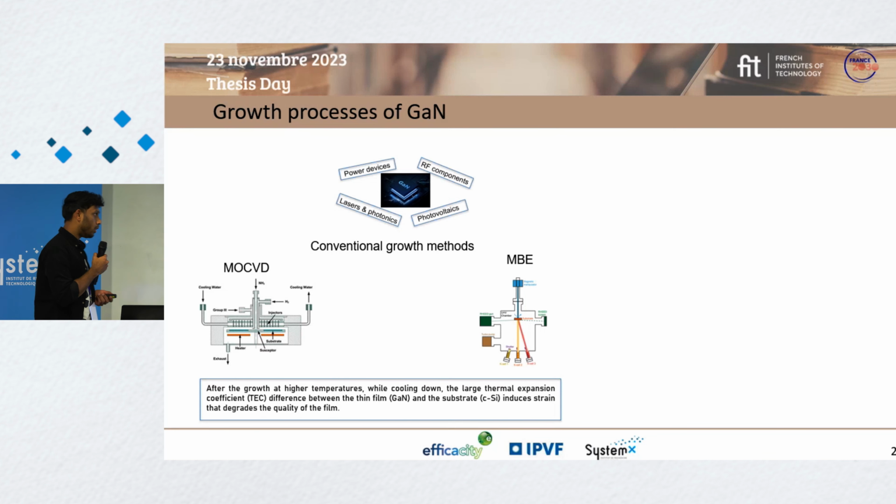the growth, while cooling down, the large thermal expansion coefficient difference between the thin film and the substrate itself induces a strain in the film, which in turn degrades the quality of the film.